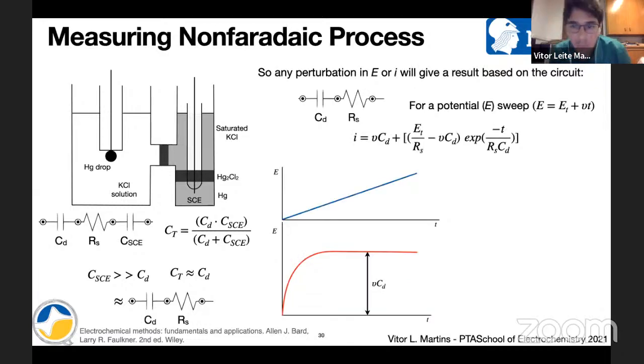Okay. So back to sweeping potential. So the current that we are measuring will depend on the sweep rate, right? On the rate that we are changing the potential, on the potential, on the resistance of the solution, because the current is going through here. And we have an exponential term here related with time. So this blue line here is how the potential is being controlled. So we are controlling potential. So we are increasing potential over time. And the slope of this blue line here, that is what we are controlling, is the scan rate, right?